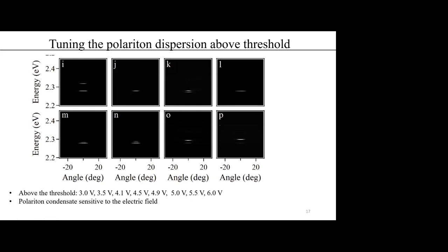So similar effects can be observed on our threshold, where the polariton condensate can be tuned by the electric field. Before and after 4.5 volts, we can see that the two branches with opposite parity and also general linear polarization are either approaching or repelling each other. Under the voltage of 4.5 volts, the two modes are degenerate.